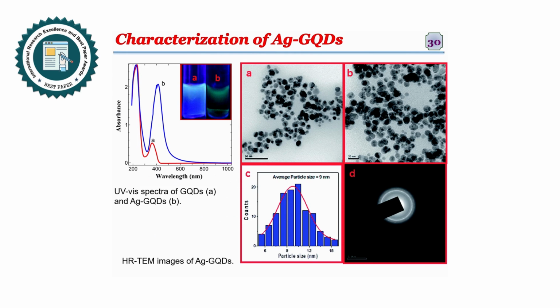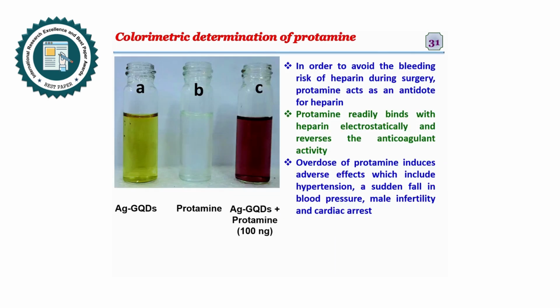The synthesized GQDs and the silver GQDs are characterized by UV-visible spectroscopy. The UV-visible spectrum of GQDs exhibited a peak around 360 nanometers, and after forming the silver nanoparticles, there is a formation of a new band around 400 nanometers, characteristic of SPR, surface plasmon resonance, of silver nanoparticles. The GQDs exhibited blue luminescence, and after forming the silver nanoparticles, the luminescence is quenched, because the surface of the GQDs is covered by the silver nanoparticles. The silver GQDs are characterized by HRTEM analysis, and spherical particles with an average size of 9 nanometers are observed.